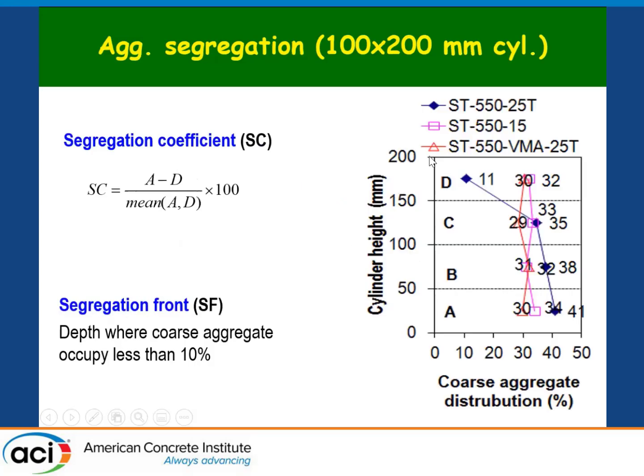So here's an example of these 3 mixtures. The first one I just showed that has segregation is the one that is in blue. And here we're evaluating the density of the coarse aggregate. You can see that there's about 11% coarse aggregate at the top versus about 34%, 41% coarse aggregate at the bottom. So the segregation coefficient basically is the amount of coarse aggregate at the bottom minus the top divided by the mean. And then we also looked at the segregation front as I presented earlier.